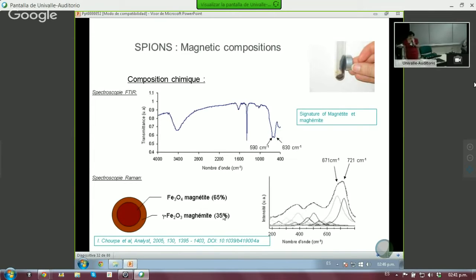Now, this is a very interesting concept because, as you know, you cannot tell the difference by X-rays, okay? Because the X-ray spectra of both iron oxides, maghemite or magnetite, are essentially 100% identical. So from the X-rays, you cannot tell. Another method you can use to tell the difference between the maghemite and the magnetite is Mossbauer spectroscopy. Of course, with Mossbauer you can tell the state of iron, but you have to have a Mossbauer to do this. So anyway, using something standard that everyone has available, like Raman spectroscopy or FTIR spectroscopy, will help in telling you exactly how much of each you have.